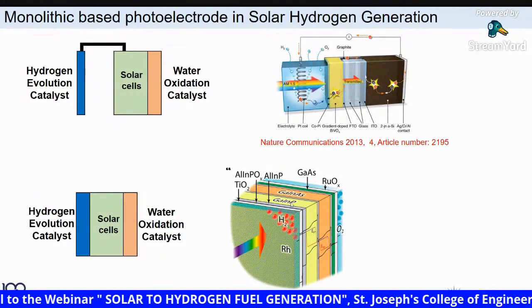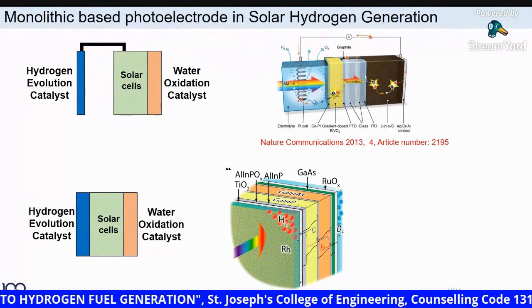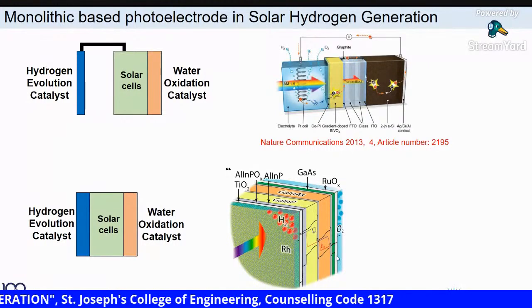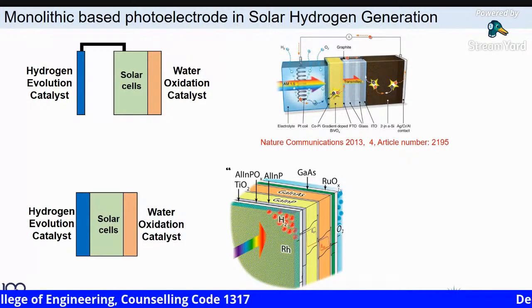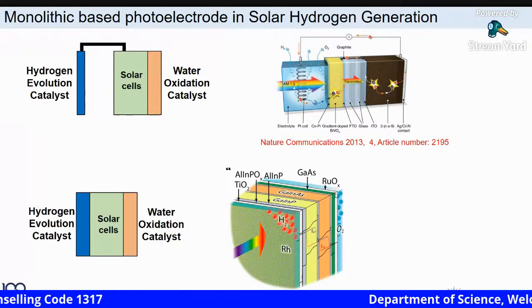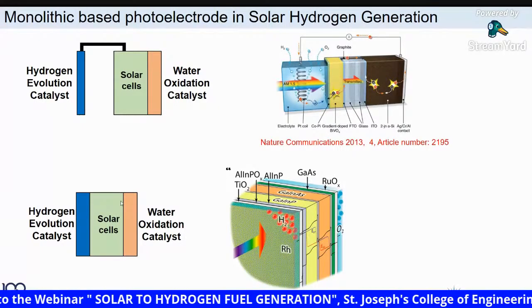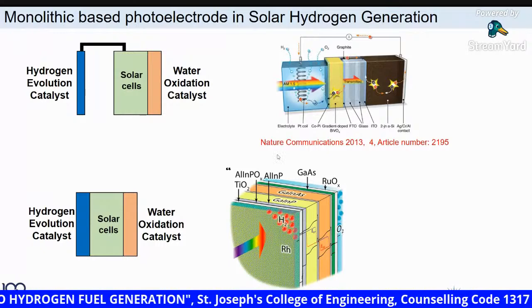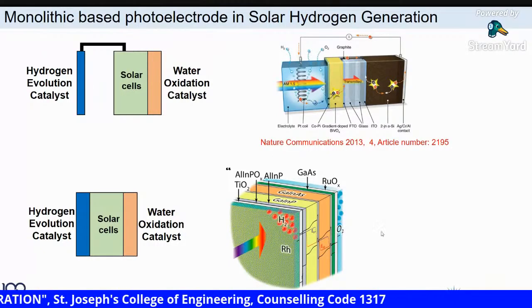So this is the solar cell, gallium arsenide and aluminum indium phosphide, and on the front end they coated ruthenium oxide. Please be careful, understand that this doesn't work under light. This is a dark cathode. They utilize the solar cell. Overall, the monolithic structure is showing a very good performance.